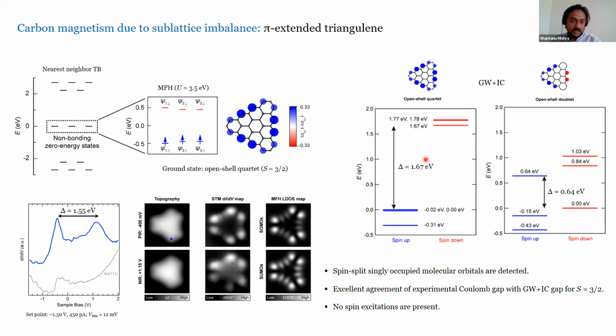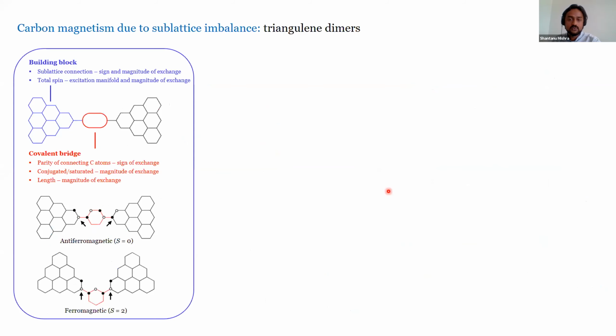The experimental gap matches pretty well with the open shell quartet state, but it differs significantly with the doublet state. So this gives us some confidence in saying that this molecule preserves its intrinsic magnetic state on the surface. However, we do not detect any spin excitations, which would be a much more direct proof of magnetism. In order to do so, we make their dimers, and that's my one picture on